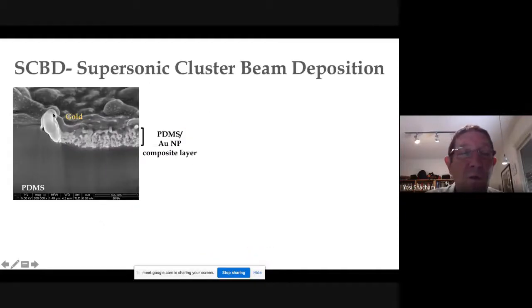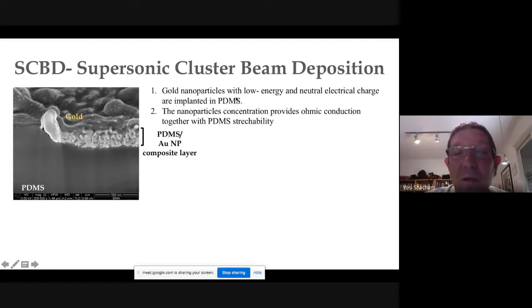And this is how it looks. This is a supersonic cluster beam deposition. This is PDMS, the polymer. And you can see if you implant enough gold, this is the PDMS with gold nanoparticles. It's a composite material, a porous material. It's approximately 50% gold, 50% PDMS. But you can see that the gold, and you can even make it more. And what happens, this is a very, very flexible material. And the gold nanoparticles, with low energy and neutral electrical charge, are implanted in PDMS.